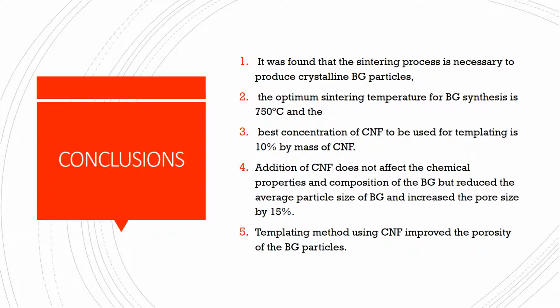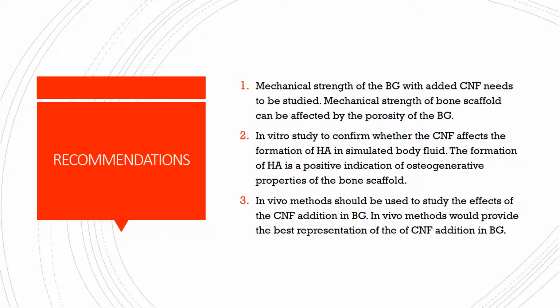Furthermore, it was also conclusive that the addition of CNF does not affect the chemical properties and composition of bioactive glass, but reduces the average particle size of bioactive glass and increases the pore size by 15%. Therefore, it can be concluded that the templating method using CNF improved the porosity of bioactive glass.